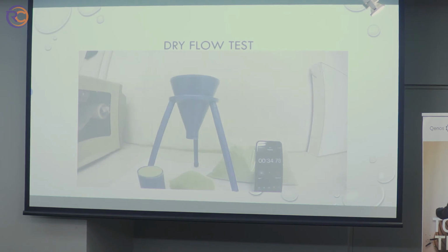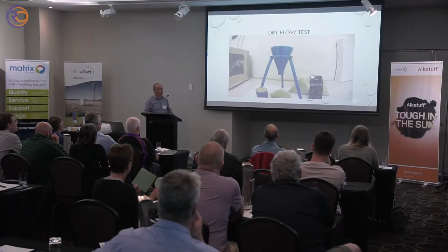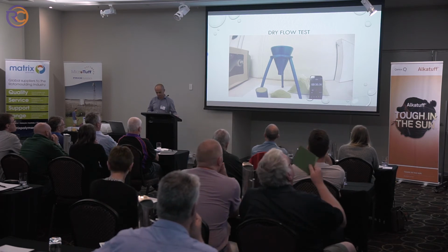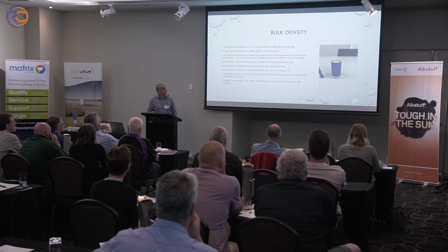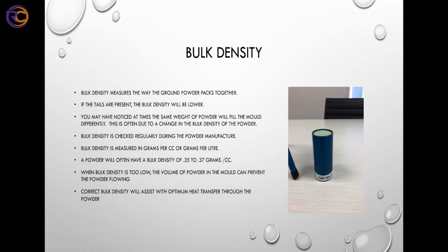So we're just skimming off the top there of the bulk density cup, and that will be weighed. And basically the weight of the powder determines the bulk density. So the bulk density measures the way this ground powder was packed together. If the tails are present, the bulk density will be lower. You may have noticed when you're moulding that sometimes you can get more powder into the mould. It seems like the powder is taking up more area in the mould than what it should. This is relating to the bulk density.